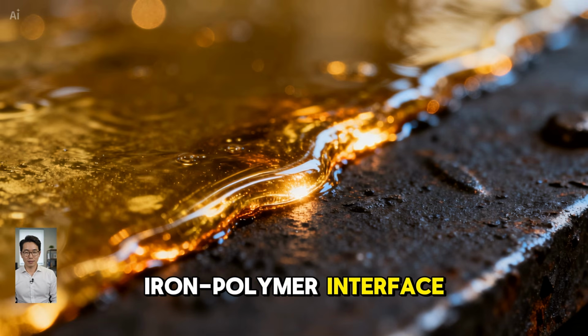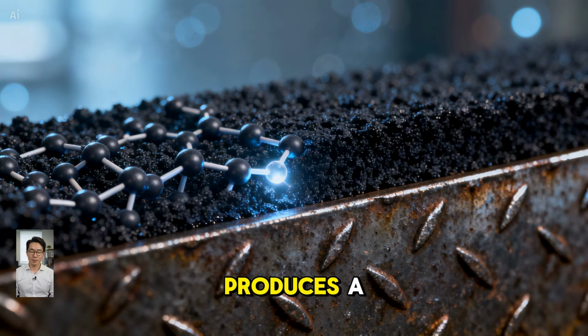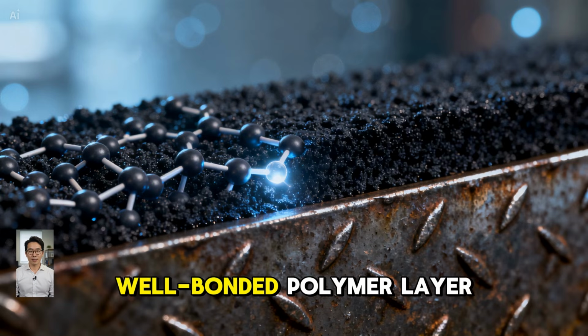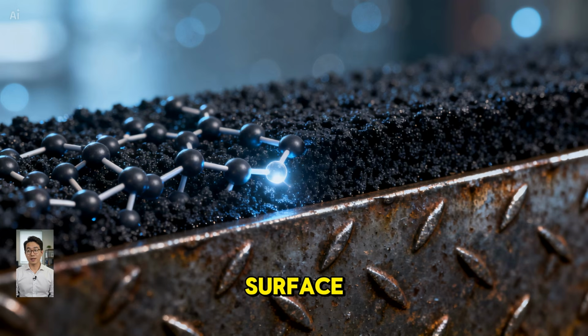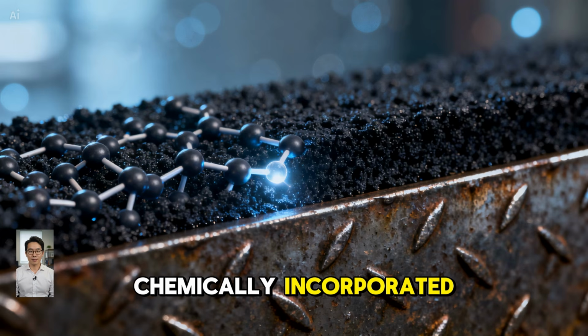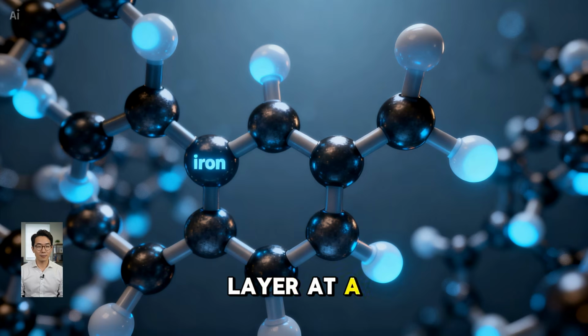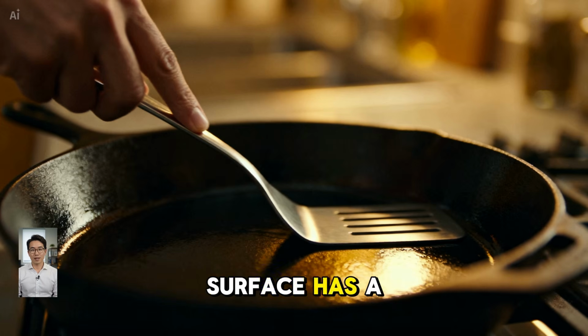at the iron-polymer interface. This catalytic effect produces a particularly dense and well-bonded polymer layer at the iron surface, with the polymer chains chemically incorporated into the iron oxide layer at a molecular level rather than simply adhering physically. The resulting polymer surface has a hardness and adhesion to the iron substrate that common cooking oils cannot achieve.